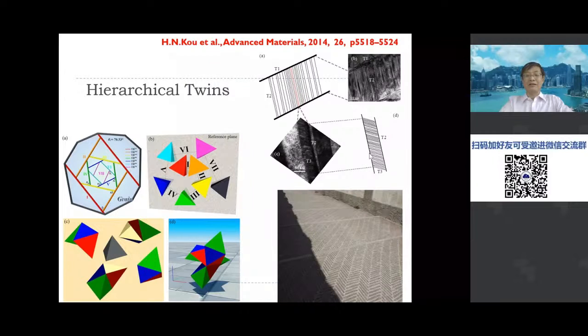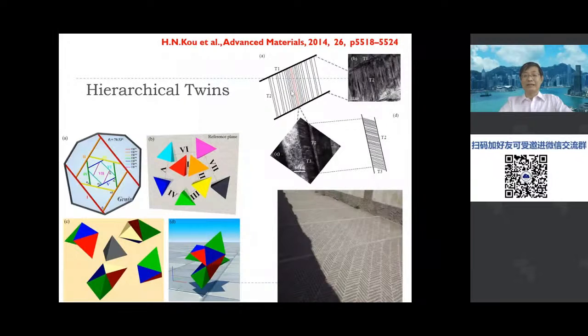As you all know, nanotwin is a very good element or ingredient to obtain the high strength, high ductility. So you can see here, on the right hand side is an example of the three levels of hierarchical twin. You have first T1, which is annealing twin, and by mechanical loading, you can generate a second order twin, and during the final loading, that second order twin has enough space to generate third order twin, so that the structure and the mechanical property of the material is high strength, high ductility material.